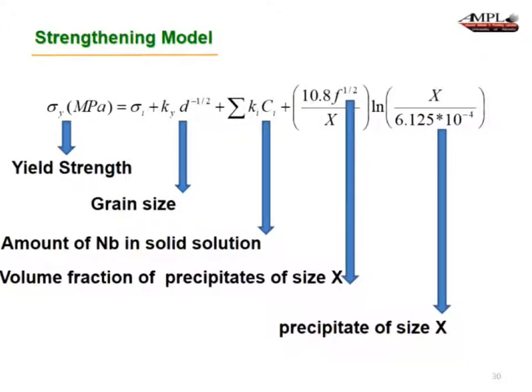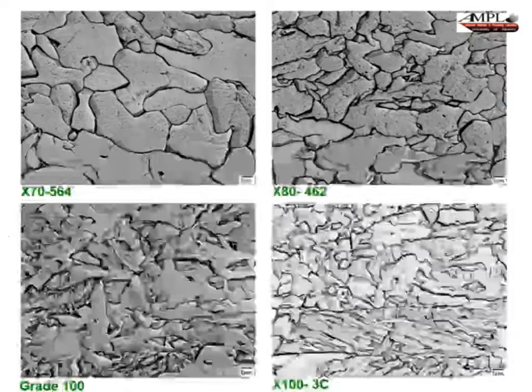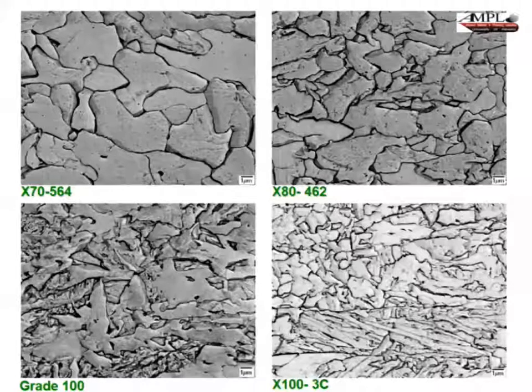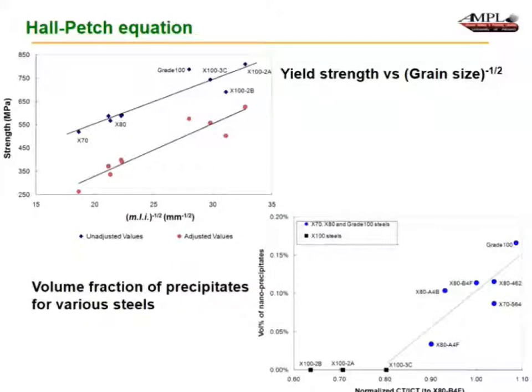So then we look at the strengthening model where this is the yield stress, this is grain size strengthening, solid solution strengthening, and this is strengthening from precipitates. And I'll come back and show you this again in a bit. So this is measuring grain size for different representative steels that I showed you in the list before. And here you see the strength as a function of mean linear intercept to the -1/2. They follow the Hall-Petch relationship pretty well.